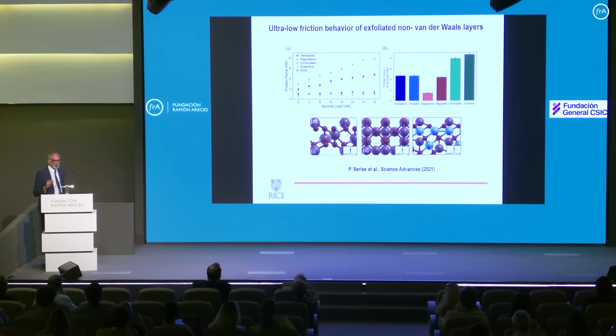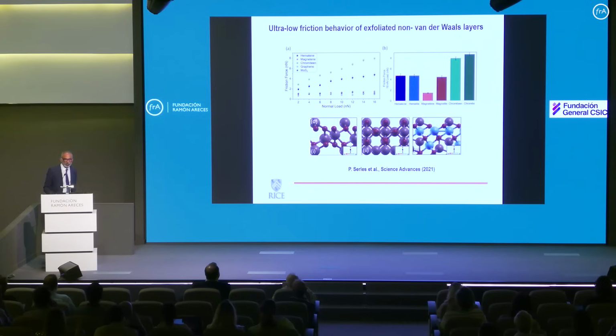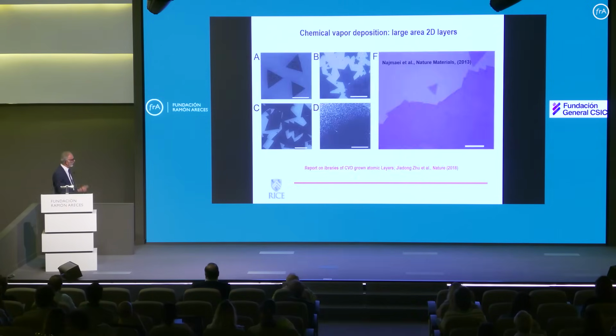And many of these 2D materials have fascinating properties. I'm just giving you one example. One of these structures that we created from a bulk material by exfoliating, we found that there is an extremely low coefficient of friction, which means that these materials, if cleaved along certain crystallographic directions in the bulk material, show extreme smoothness, or almost atomically smooth, which means that they can be very, very slippery, with a very low coefficient of friction. Just one aspect of this 2D nature.